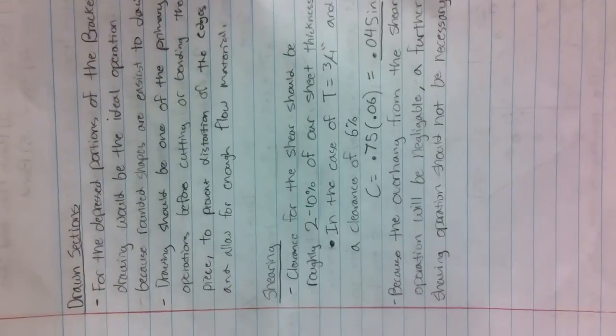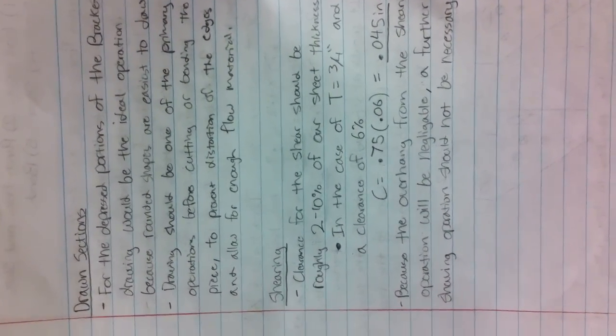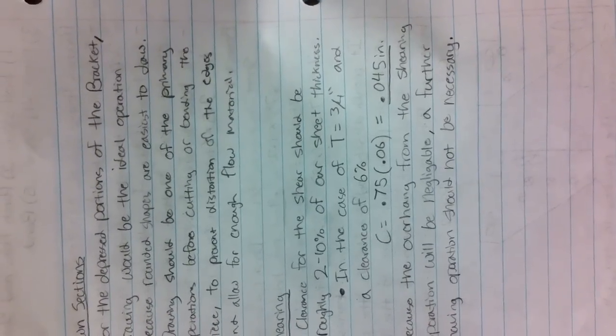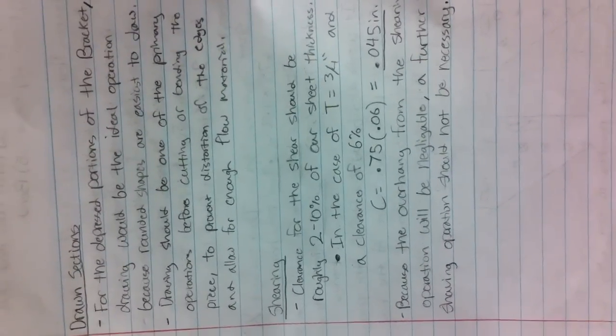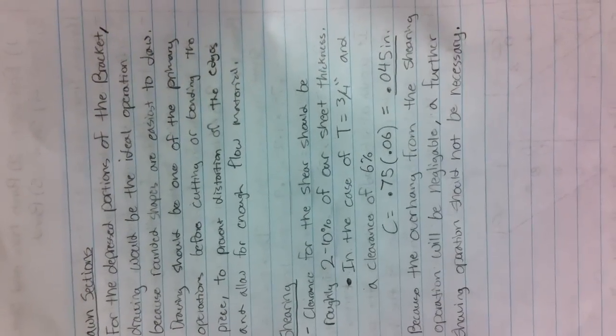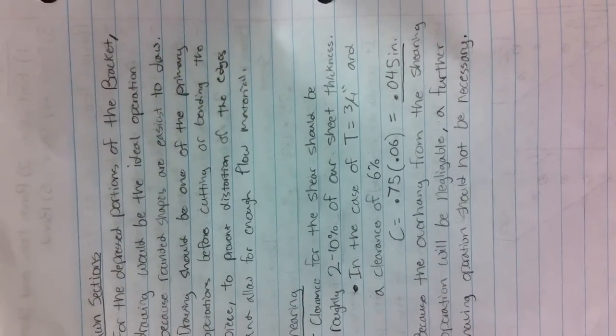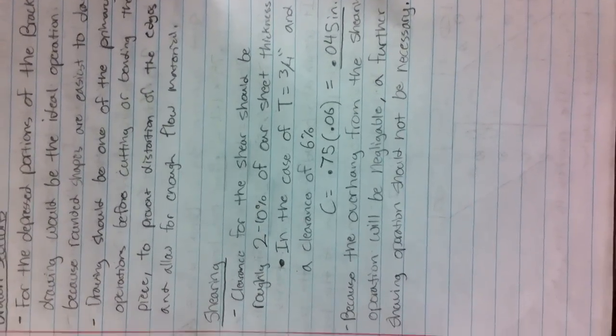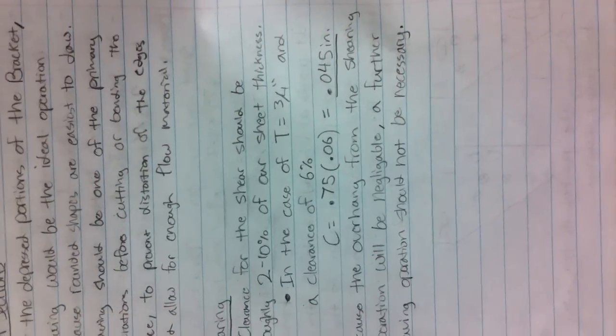And then for the shear, the slides say that you should keep the clearance for the shear between 2 and 10% of the sheet thickness. From our example before, if we had the thickness at 3/4 of an inch and say a clearance at around 6%, you say 0.75 times 0.06. So then your clearance would only be 0.045 inches, which is pretty small, and because this is negligible, you wouldn't need a shaving operation, just because there's not enough material to really shave off there, and it really wouldn't affect the part very much, and we'll save money.